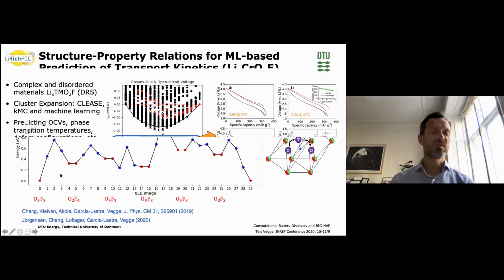And we simply cannot use the traditional energy difference to map out the barriers associated with transport throughout the system. We need to know in more detail what the lithium concentration is, which cations and anions are present surrounding the jump before we know if a jump is accessible or not.